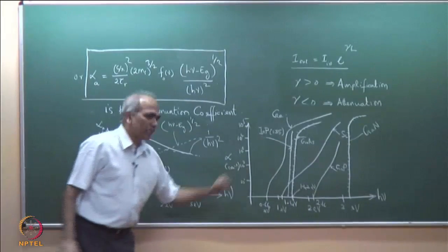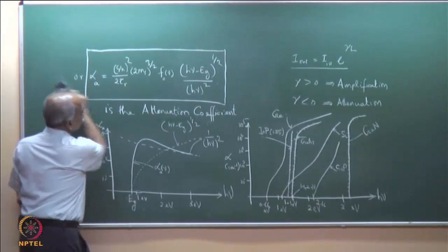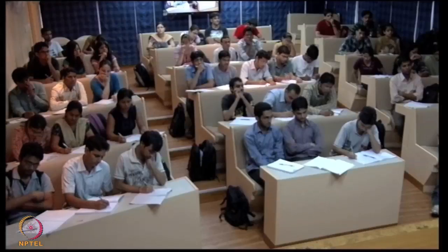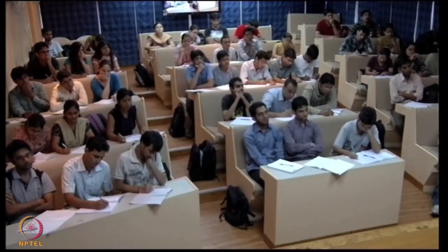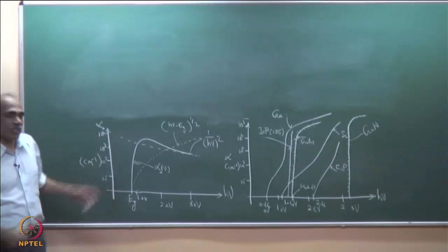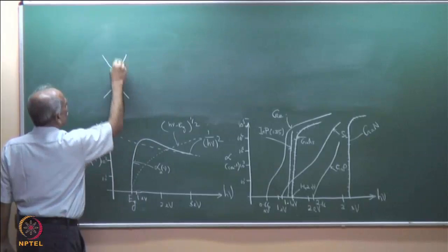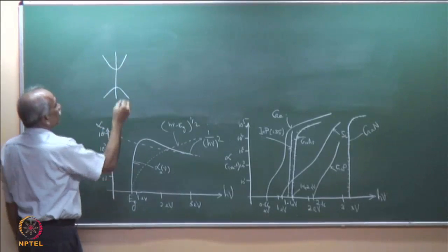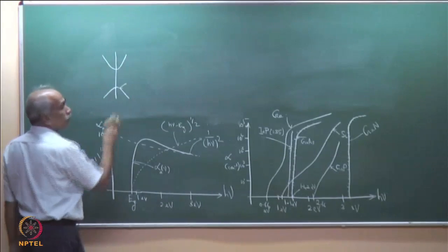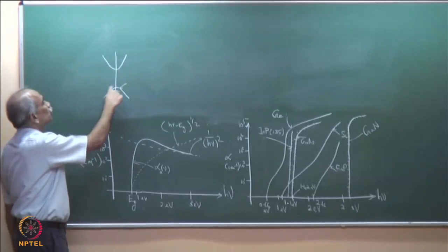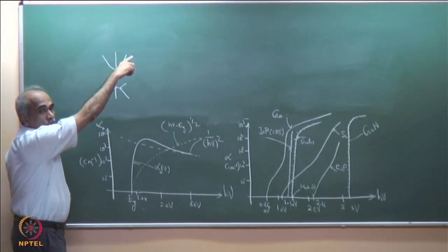There are several explanations that are due. This graph that we have obtained considers a direct band gap semiconductor, and we have concentrated only on the parabolic approximation close to the band edge. These bands do have very different behaviors away from it.